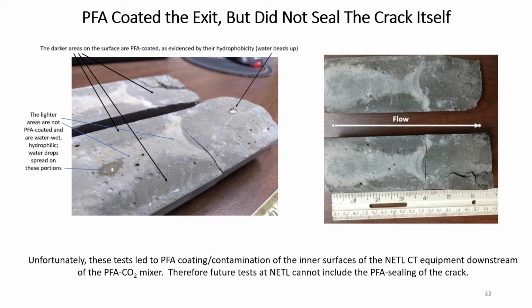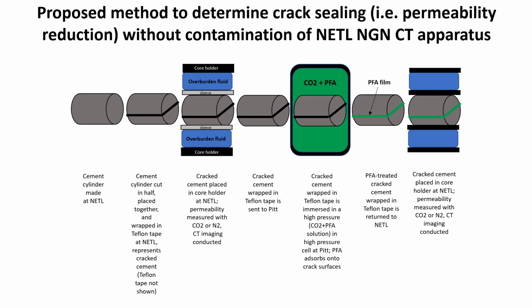Unfortunately, though, these tests led to significant PFA contamination of the equipment at NETL, so we will have to try other methods for future tests. Our next attempt then will be for NETL to supply us with cylinders that we will put in the Robinson cell with a solution of pressurized CO2 and PFA. We will then let it sit for 24 hours so that the PFA adsorbs in the crack and return it to NETL Morgantown for CT and permeability measurements.